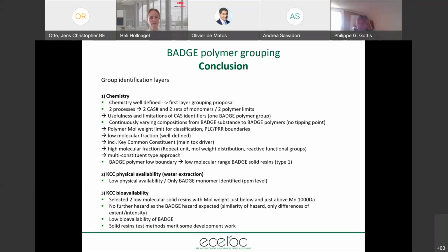Two resins were selected at the low boundary of the polymer range in scope for so-called bracket testing, with average molecular weight bracketing 1,000 Dalton. The two resins, both as produced and without BADGE, were tested. The results show overall no bioavailability of BADGE from the solid polymer resins in scope, but some inconsistency involving the purified versions suggest that the used test methods are not fully suitable for polymers and merit some adaptation work. With that, I'm done. Thank you very much.